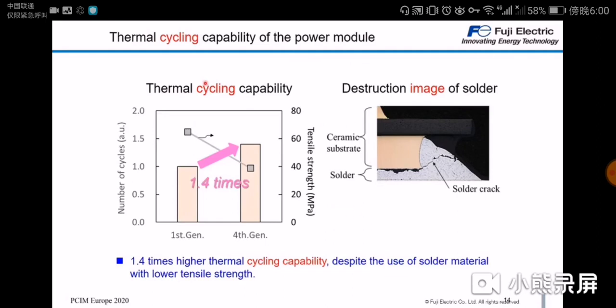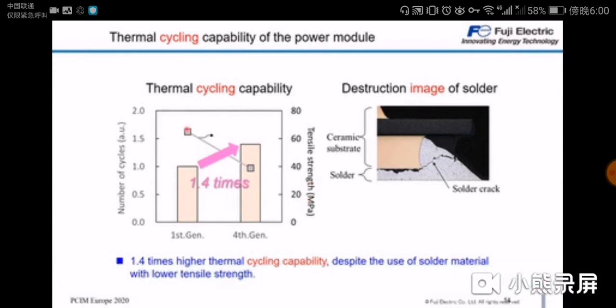And here we can see the thermal cycling capability in a little more detail. This graph is showing the number of cycles that the first generation could withstand, and on the right side we can see the number of cycles that the fourth generation could withstand. We were able to increase this by 1.4 times, even though the tensile strength of our solder material, shown in these gray blocks here, has become lower compared to the first generation.